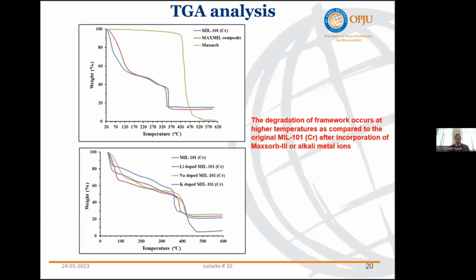Okay, so basically we have done the TGA analysis to study the thermal stability of the synthesized material. That means how much temperature this material can withstand, that is, at what application temperature this material can be used. For that, we have done the thermogravimetric analysis. If you see here, until 100 degrees centigrade there is a weight loss. This weight loss corresponds to the desorption of water molecules inside the MOF structure.